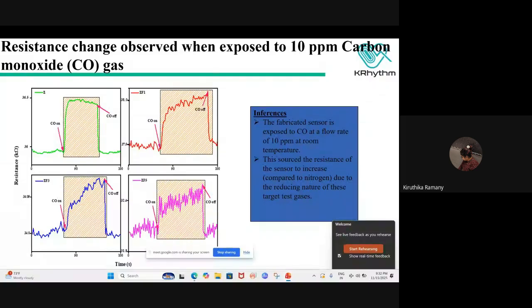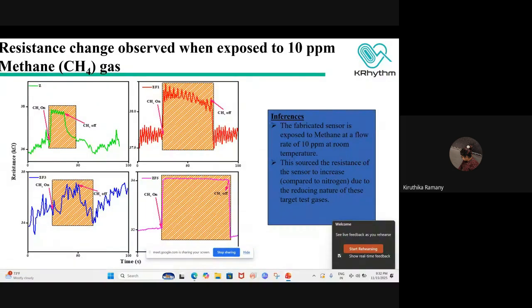So from this, we will be calculating the sensitivity, that is the ratio of the resistance under test gas to the baseline resistance of the sensor before exposing to the target test gases. So this is the resistance change that we observed when the same sensor was exposed to 10 ppm of methane test gases.